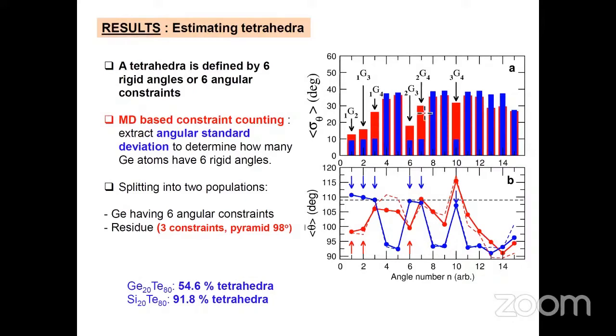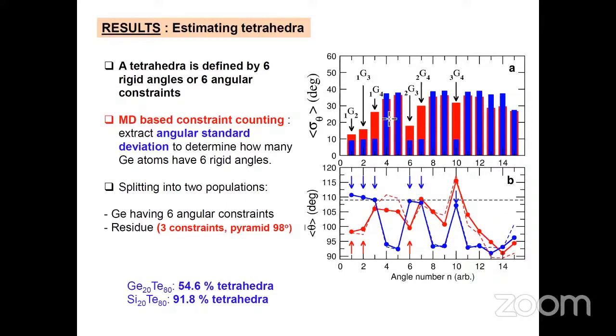The other population, as you can see, has a much larger angular excursion for select angles. We can see angle number 3 or number 7, number 10, and we have basically only 3 small standard deviations for those germanium atoms. So now we have identified those atoms, we are able to calculate their corresponding average angle. And we can nicely see that those blue bars give rise to angles which are about the tetrahedral angle, whereas the germanium atoms which have only 3 rigid angles, so the angles 1, 2, and 3, give rise to an average angle which is about 98 degrees. So we are able to split the population into germanium having 6 angular constraints, which are tetrahedra, and a residue, which has only 3 constraints.